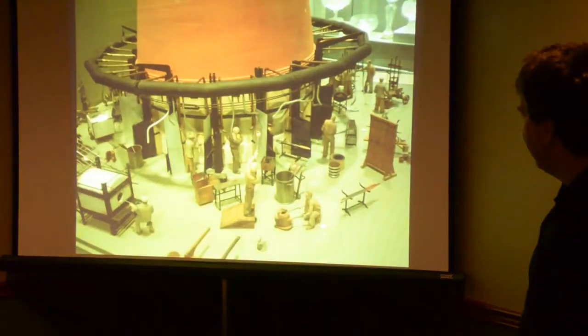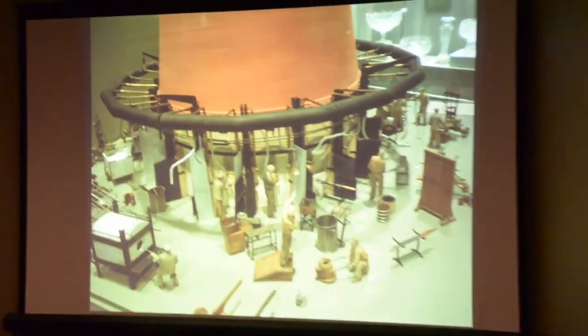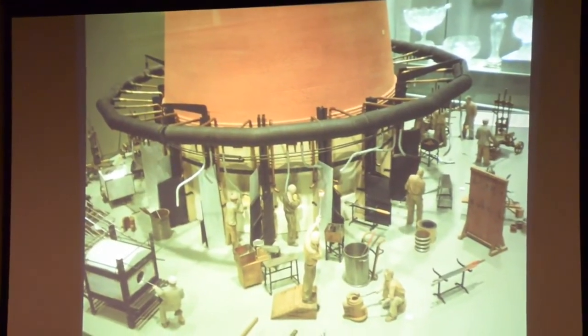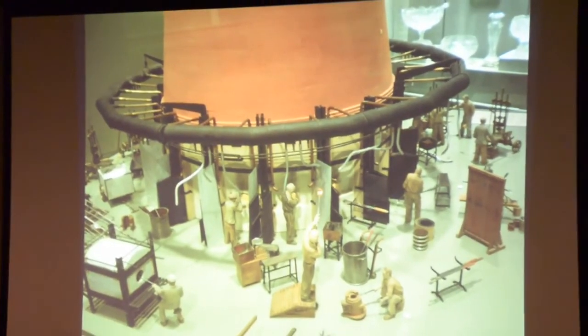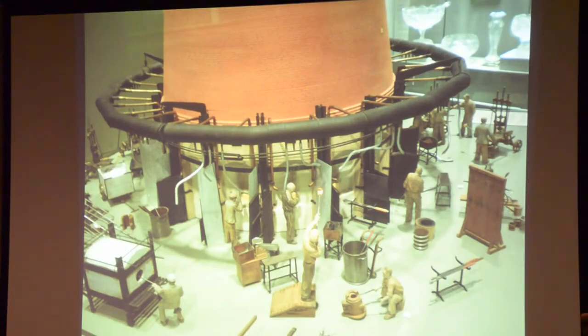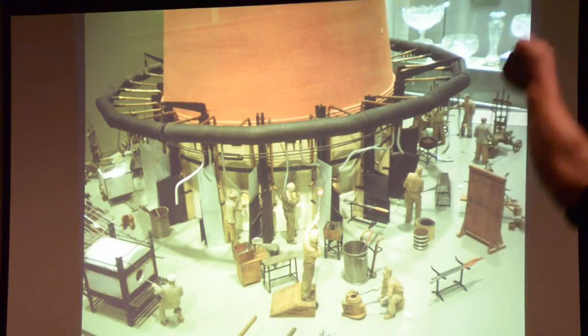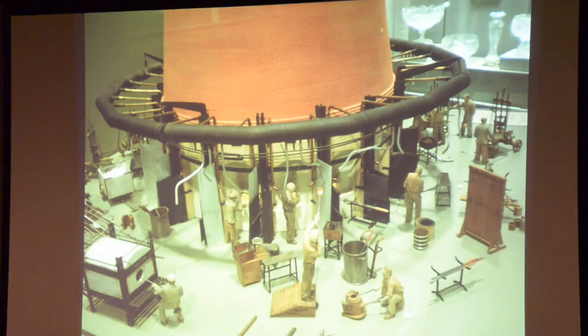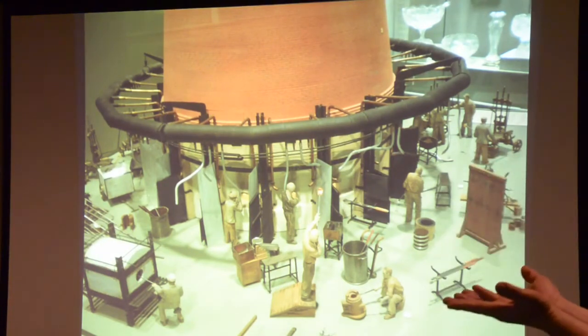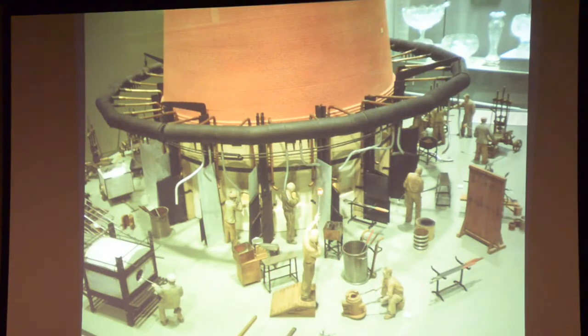Before Pilkington, they were doing some agonizingly laborious processes for making flat glass. This is from CMOG, and it's a nice model of how the shops used to be. Here they're making small vases in a production capacity, but in a similar process, they'll make flat glass. They'll make a bubble of glass that's really huge, and they'll have a hole in the ground, and they'll blow and drop and blow and drop, and have a 2-story tall glass cylinder. And they'll wait till it's solid, and then they'll cut it around the top and cut it at the bottom, and they'll anneal it as a cylinder, and then they'll take it out, cut it into half cylinders, put it back in the oven, slowly bring it up to temperature, let it fall flat. And that's how they made large sheets of flat glass before the Pilkington process came around.